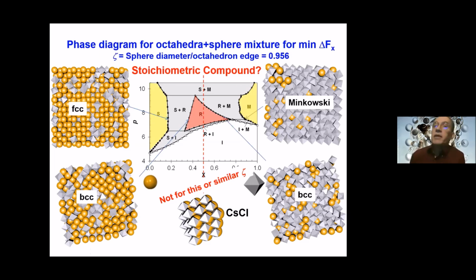Yes. We also confirmed this by creating an interfacial system. You can create a system where you start with the two putative phases, and you want to see, are they going to mix and form this R phase? So we thought, if this is an artifact, if I start with a system that phase separates between an S phase and an M phase, then they should mix. And indeed, when we put in one box the two phases S and M for the equimolar composition, we found that they didn't want to stay phase separated. They mixed and formed this R phase. So we tried to get it from multiple angles to make sure that it was a true prediction and not just an artifact.